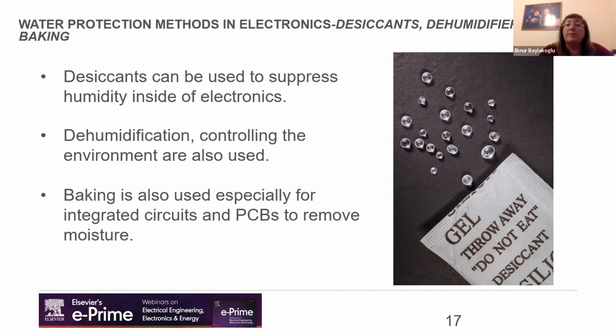And also we are applying the baking process, especially for integrated circuits and printed circuit boards, which absorb moisture and humidity from the environment. So before the assembly process, if we apply a baking process, we are able to remove their moisture inside, which prevents moisture-induced delamination and popcorn failures.